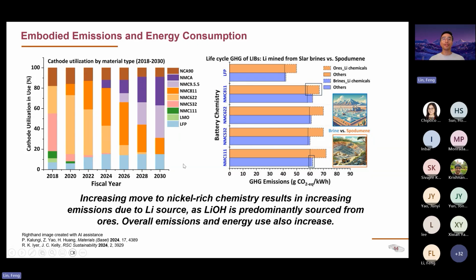So you can think of this as if the market is really driving towards high energy density. Nickel-rich NMCs are probably going to play a very important role, because nickel-rich can provide much higher energy density than lithium iron phosphates and other low-nickel versions of the cathodes. So if we believe in that assumption, then we get to think about how these types of materials are being